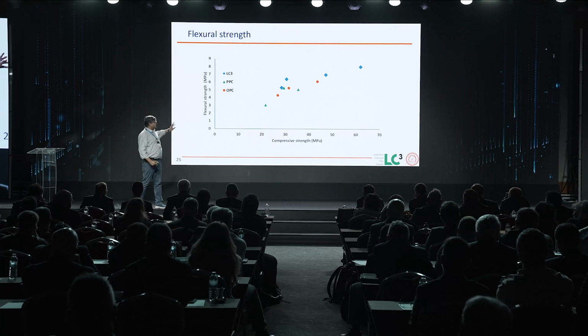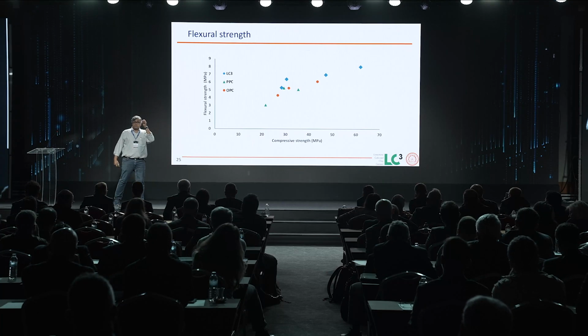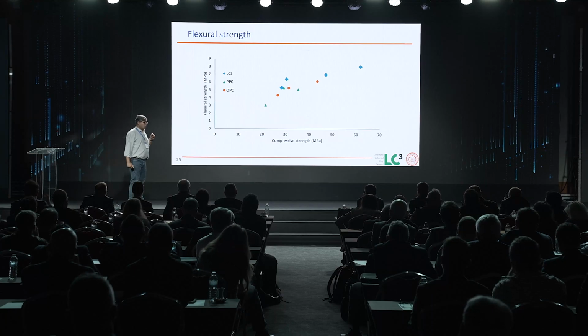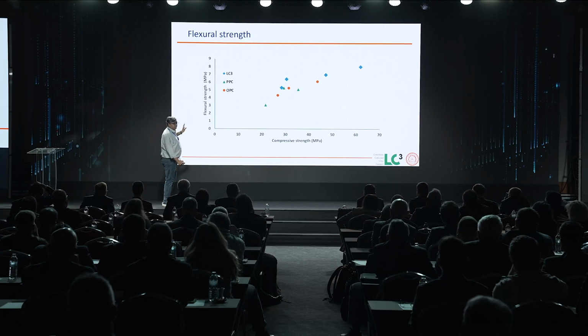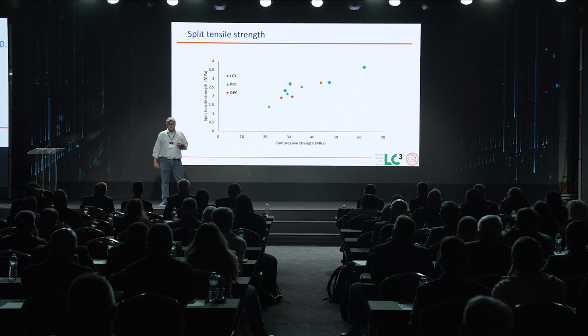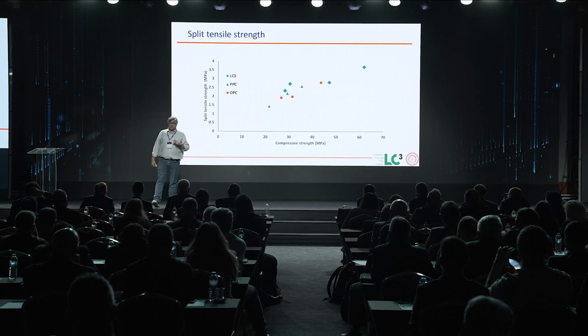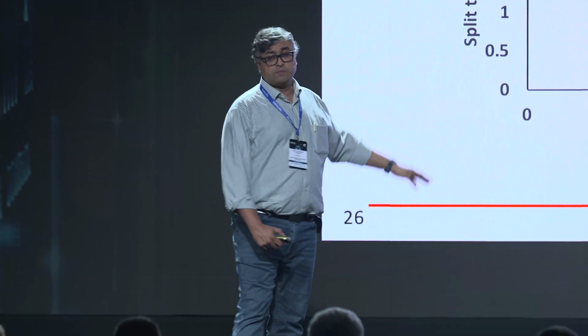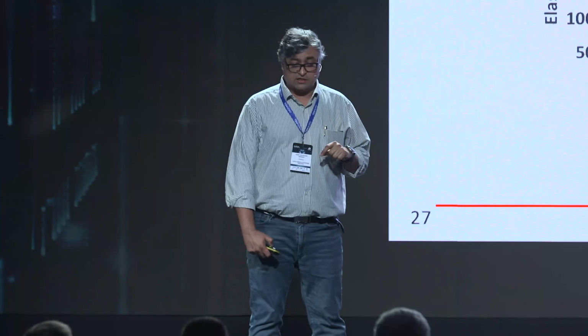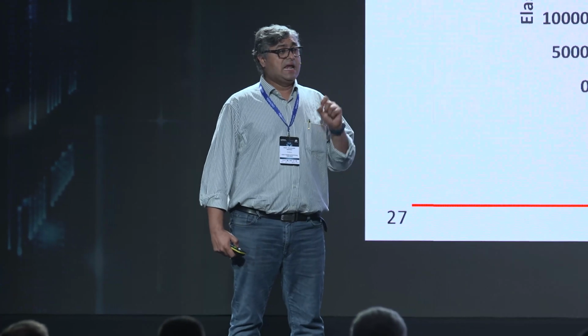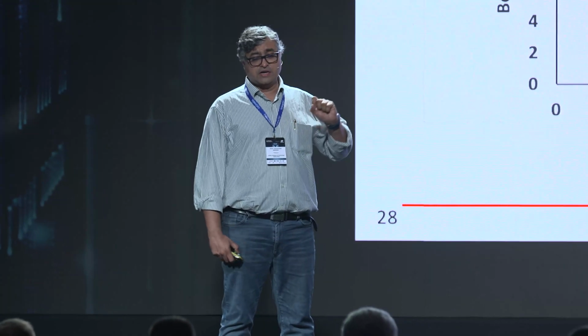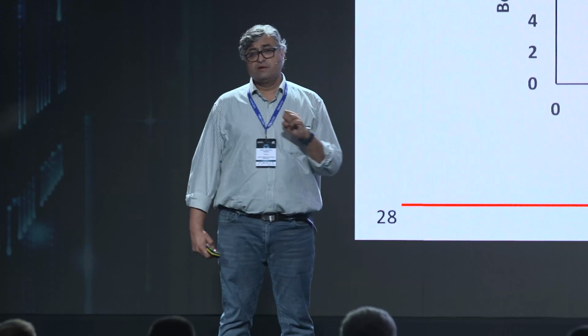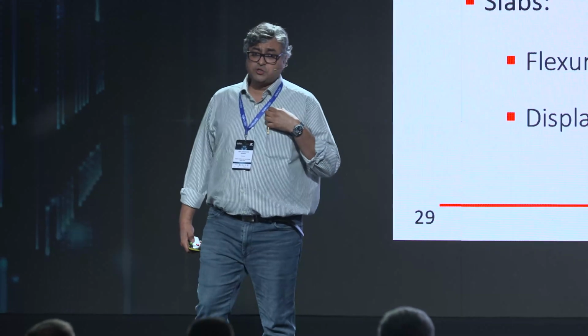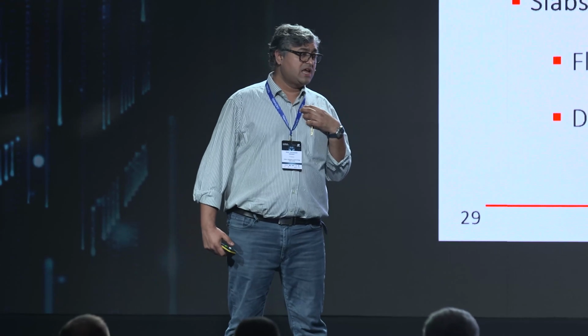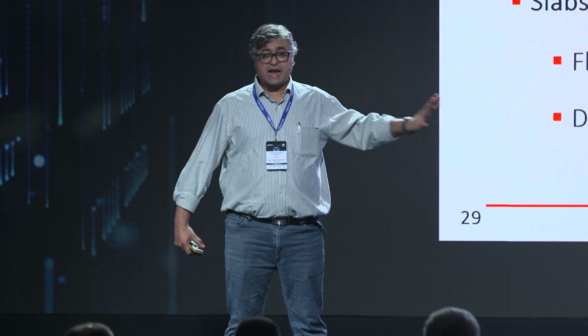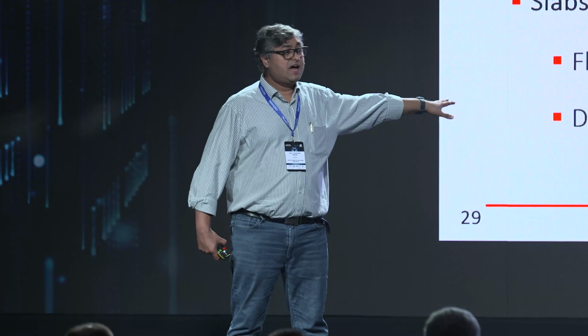You need the flexural strength. Once you have achieved the compressive strength that you want in your concrete, you will get pretty much the same flexural strength as any other cement. Once you have achieved the compressive strength, you will achieve pretty much the same tensile strength in the concrete, pretty much the same elastic modulus of the concrete, pretty much the same bond with the reinforcement. So I'm also a structural engineer. As a structural engineer, I'm not worried about the mechanical performance of the concrete,